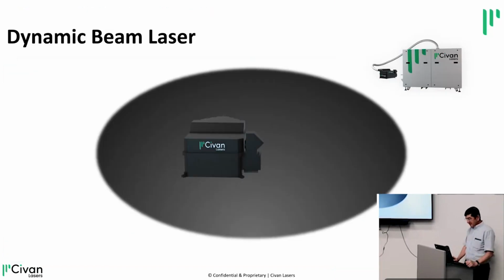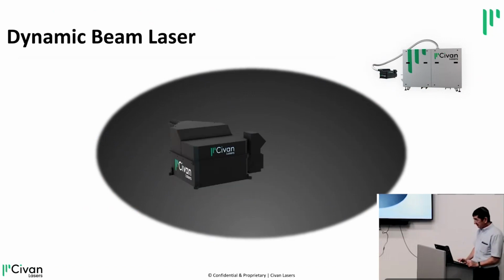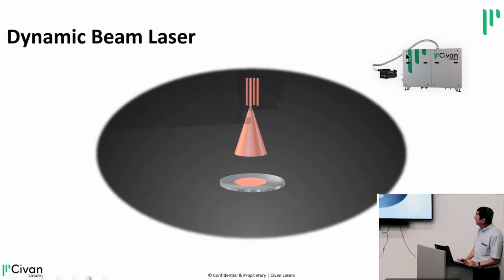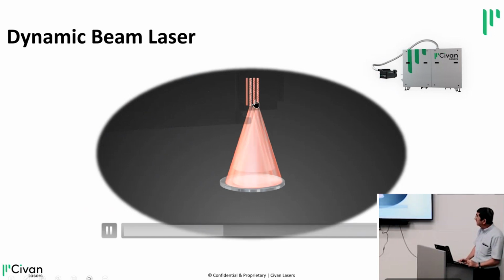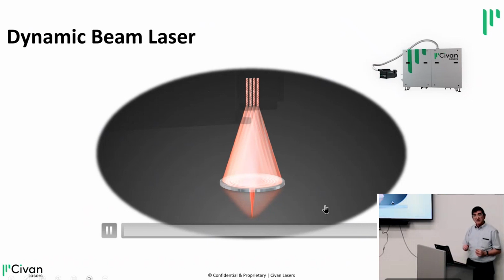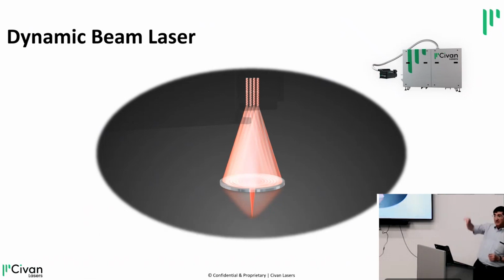Okay. So in reality, that's what it looks like. You see the laser and the fiber going to the optical head. And from the optical head, you have tens of beams coming, overlapping, and on the workpiece, they're all focused to one point, and instead of being a few hundred microns, they're just a few tens of microns, and can move from place to place, both X, Y, and Z. You can also move it up and down, because basically with the phases, we create a virtual lens, so we can have full control on the position of the beam. So this is the core technology, this is the core capability, and now I'll explain why it's important.